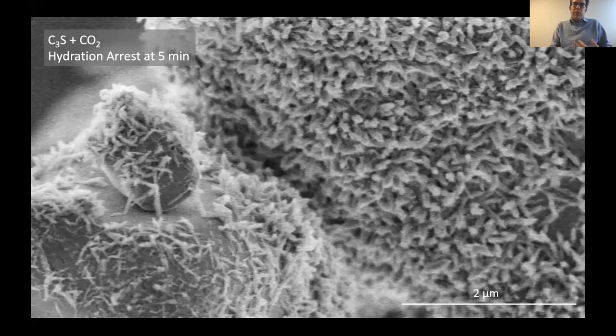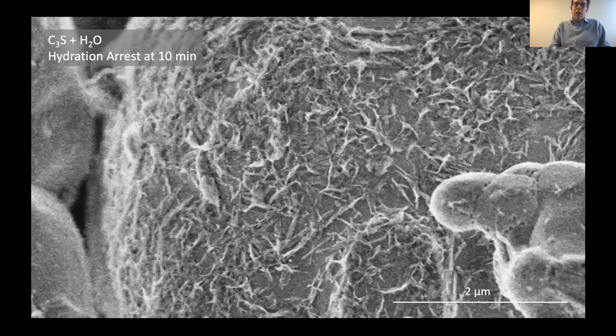So after 5 minutes of hydration, we have a lot of activity in the system. So we have new gel has formed. We don't see the discrete particles anymore. They've been kind of buried by a lot of the new product that's formed. And if you compare that to something that had no CO2 in it, we can find maybe a reduced evidence of the reaction phase. So what's happening is the addition of CO2 is just kind of kicking off hydration, and somehow, some way, the phase assemblage is leading to a compressive strength benefit.